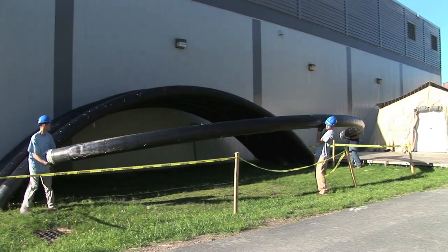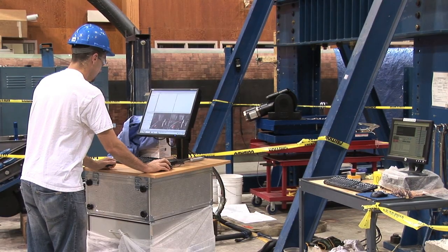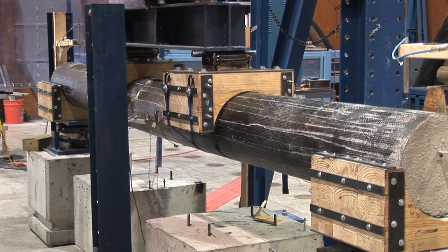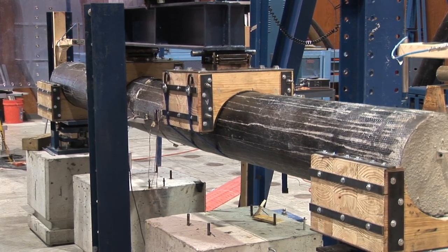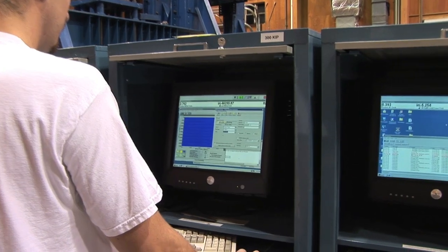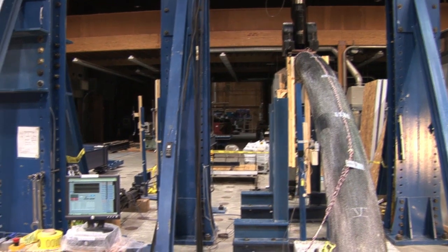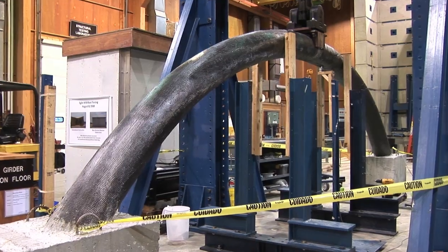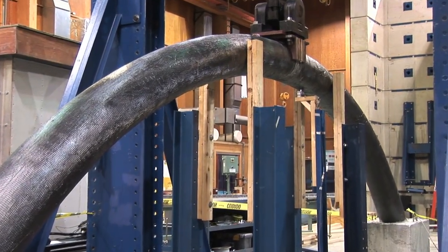These features have been tested in the lab. During the accelerated fatigue testing, concrete-filled arches were subjected to the equivalent of 50 years of truck traffic over an interstate highway bridge. Results showed that the arches retained their full capacity after the fatigue tests were completed, proving that the residual strength of the arches was equivalent to the initial strength of the arches. Moreover, testing has shown that these arches are extremely ductile compared to conventional reinforced concrete.